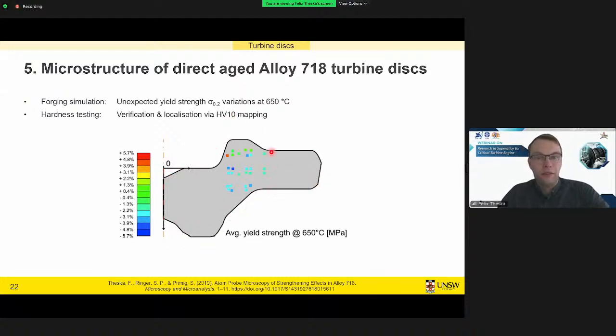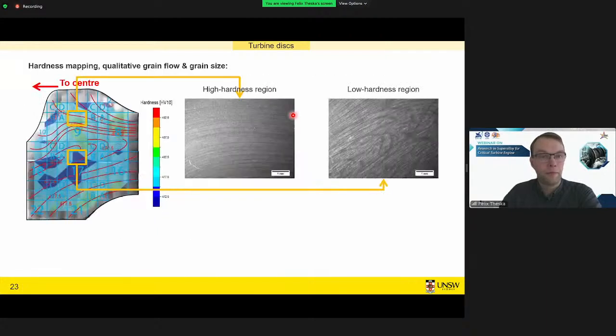And if we focus here on this middle section, we do find there's some yield strength anomalies, mostly in this middle region where it's very low. And we can reproduce this with hardness mapping. I used Vickers hardness 10 in this case. So this is a smaller section out of the same turbine disk.